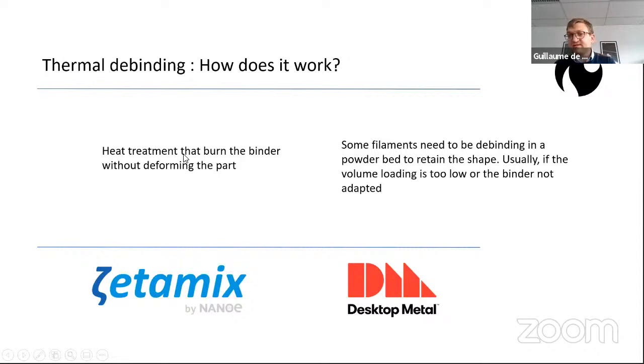You just put the part in the furnace and you heat up very slowly to burn the binder away without losing your shape. And that's not that easy to do without deforming the part. This is what we do at Nanoe, of course, for our metal material. It's also what Desktop Metal is doing with their new version of the studio system, but these are probably the only 2 players who are actually doing thermal debinding for the moment. In some cases, you will have some deformation of parts, and a few suppliers may suggest using a powder bed to keep the shape in place. This for us has a few drawbacks, so when we can, we should avoid it.